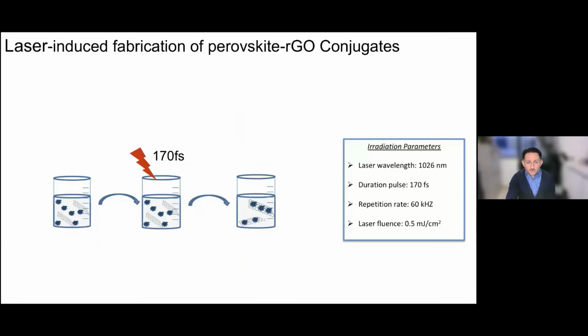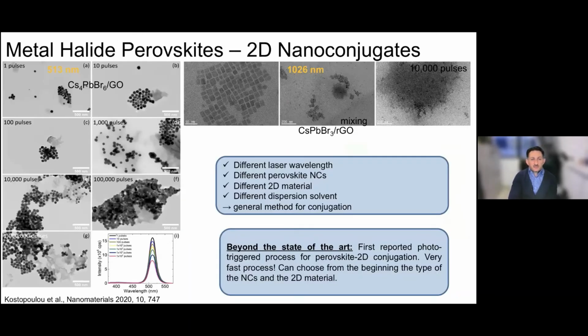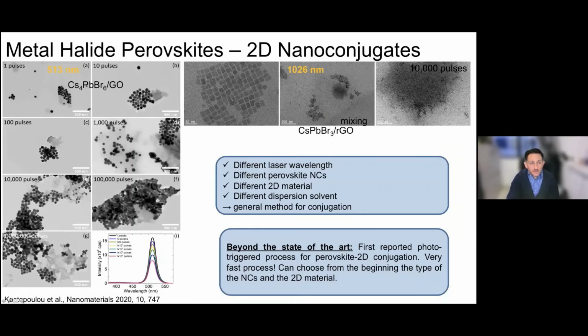To cut a long story short, we have performed this experiment. We have fabricated reduced graphene oxide conjugates with perovskite nanocrystals. This is a very simple process, in solution. These are the laser radiation parameters we have used, and these are the results. In the case of the nanohexagons, you can see how the structures and this conjugation evolve upon increasing the number of pulses at a specific fluence. And also you can see how the photoluminescence is evolving.